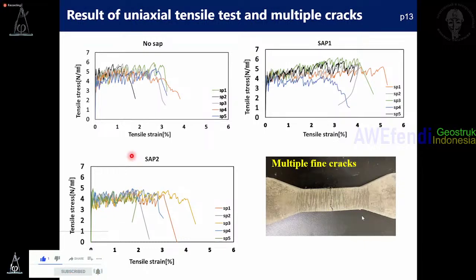But their trends are a little bit different. It seems like the SAP 1 case has the higher ultimate strength and ultimate strain, which means higher ductility. And for all of the specimens, here is one example. You can see many fine cracks at the surface until the final localization of one crack.